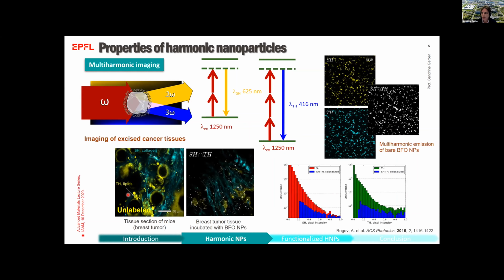After incubation with bismuth-ferrite harmonic nanoparticles and application of the colocalization procedure, you can see a clear and very selective identification of the nanoparticles, represented here by the white spot, thanks to the background rejection. In the semi-log histogram of pixel intensity at both the second and third harmonic, we have covered the whole detection range, highlighting the discrimination of the harmonic nanoparticles, shown here in blue.